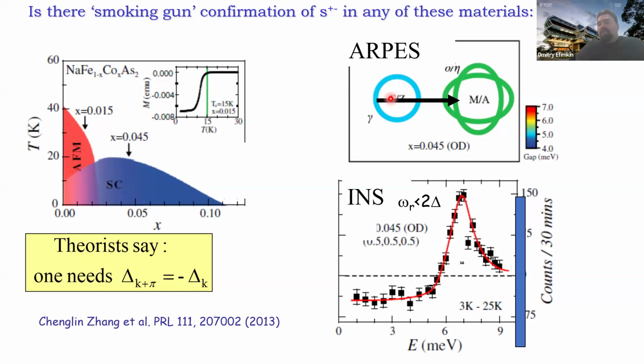In iron-based, the study with electron irradiation has been done, so that at least they could show that you can reduce Tc according to the Abrikosov-Gorkov formula. I don't know whether there have been attempts to systematically study whether you can increase Tc with respect to the residual resistance ratio. Might be that exists, but I'm just not aware of it.